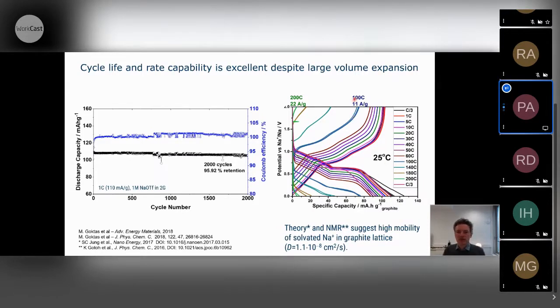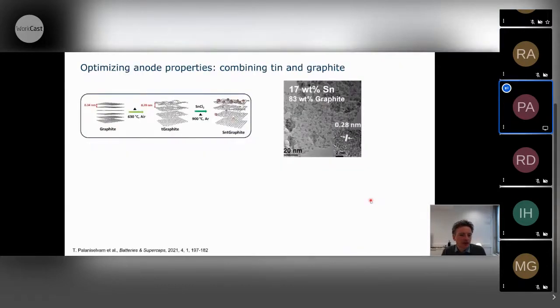And this is shown here. So this is, for example, a current density of 11 ampere per gram, and you can still get quite a decent capacity. Once again, for batteries, you want to be higher, so we need solutions to this. If you compare this to supercapacitors, this capacity is very, very high. So in a study, we used this material also as an anode material in a hybrid ion capacitor, because here it works very well, and the capacity for a supercapacitor is quite high. And this is what we did.